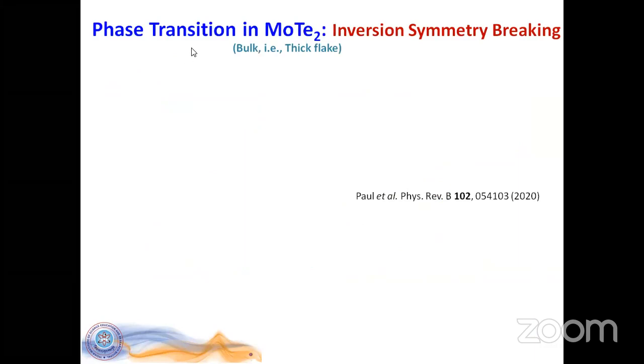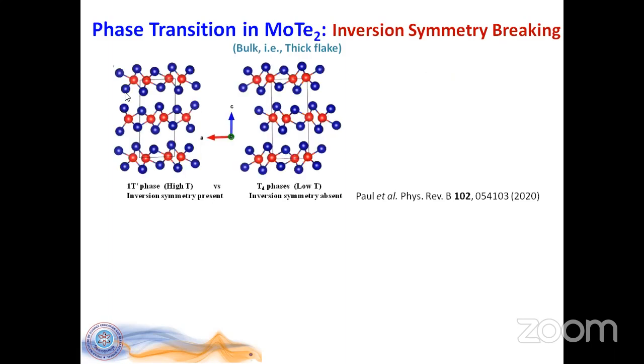So as I mentioned in the beginning that we're going to discuss MoTe2, let's see what it is about. MoTe2, when we see in bulk, basically undergoes a very well-known structural phase transition, which is because of the inversion symmetry breaking. That happens from the 1T prime phase, which retains the inversion symmetry, which is the high temperature phase. And at low temperature, it goes to a Td phase, which is an orthorhombic structure. And that's where the inversion symmetry is lost.